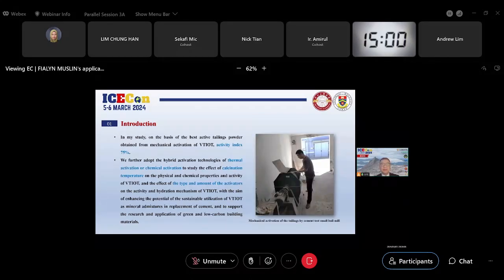In my study, on the basis of the best active tailings powder obtained from mechanical activation of VTIOT, whose activity index is 75%, we further adopt the hybrid activation technologies of thermal activation or chemical activation to study the effect of calcination temperature on the physical and chemical properties and activity index of VTIOT, and the effect of type and amount of activators on the activity and hydration mechanism of VTIOT, with the aim of enhancing the potential of the sustainable utilization of VTIOT as mineral admixture in replacement of cement and to support the research and application of green and low carbon building materials.